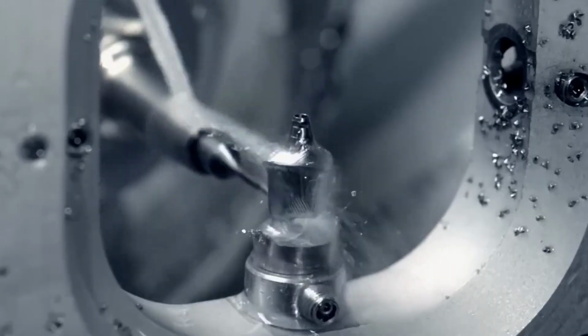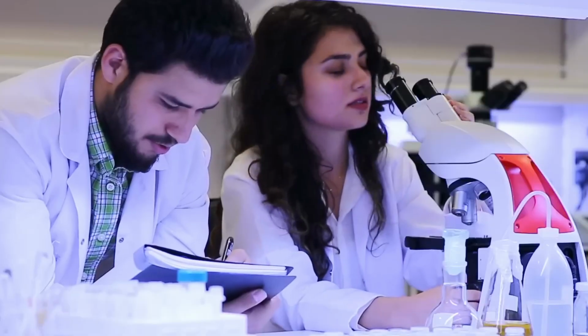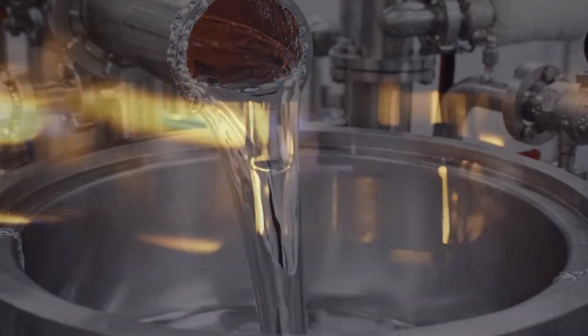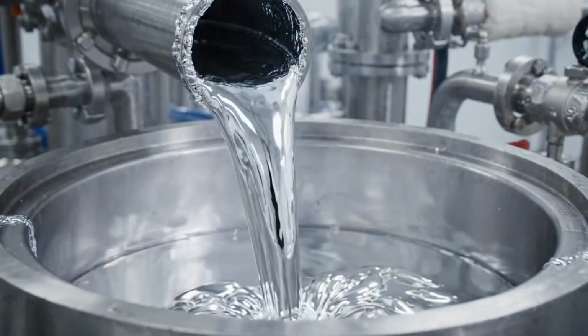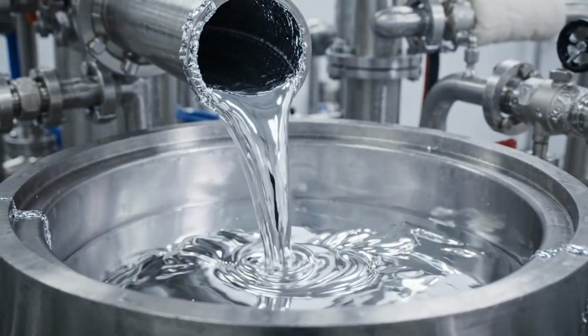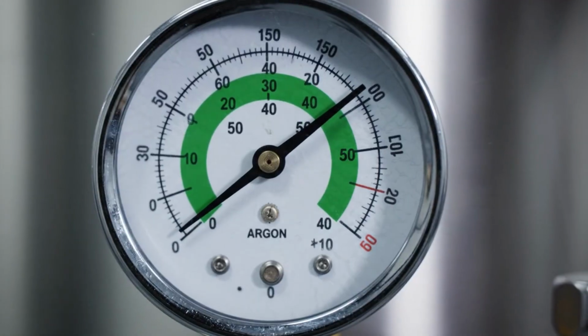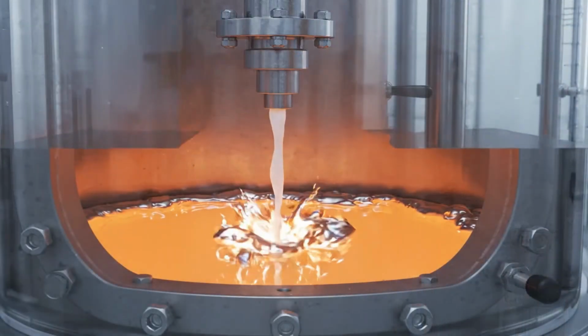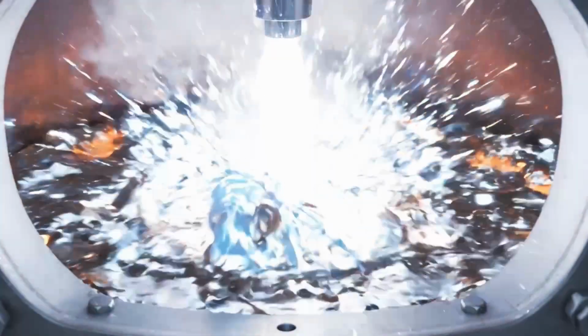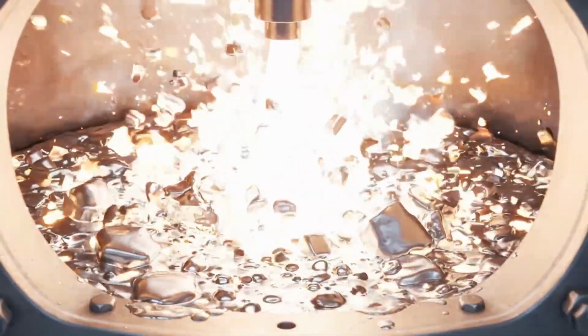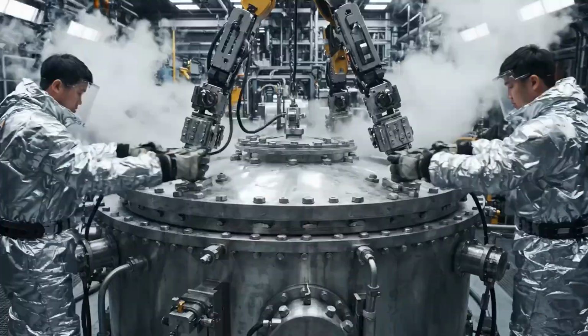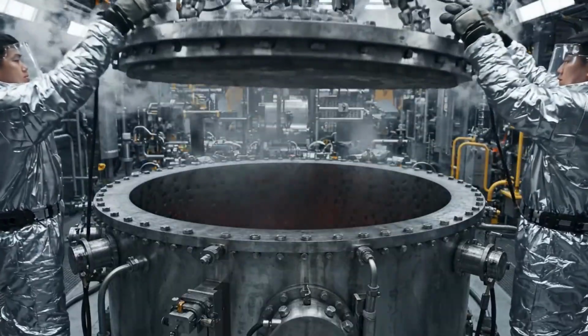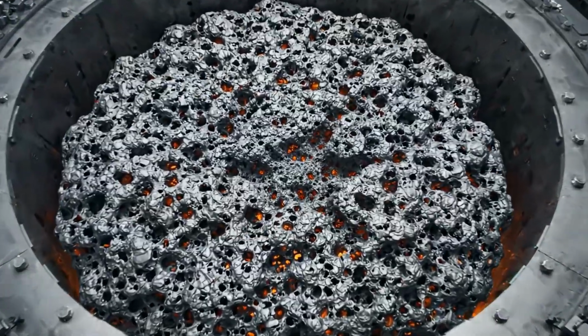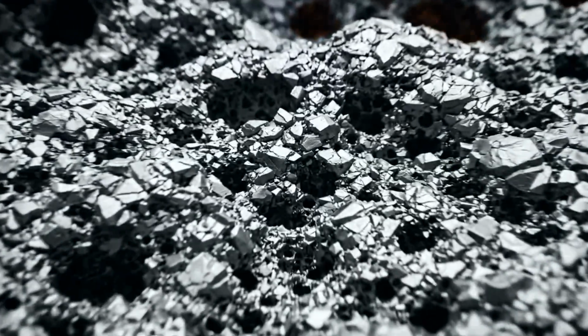Once the titanium tetrachloride is purified, the reduction process begins. Liquid magnesium is introduced into a sealed steel reactor, and an inert atmosphere, usually argon, is maintained to prevent the entry of oxygen and nitrogen. Then, TiCl4 is carefully fed in. The chemical reaction is intense. The magnesium removes the chlorine from the titanium tetrachloride, leaving metallic titanium along with magnesium chloride.